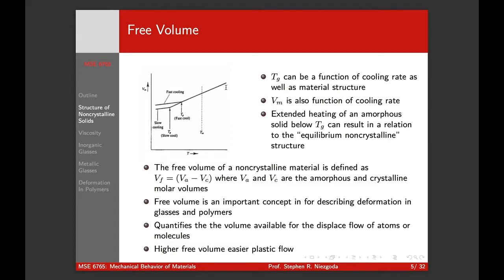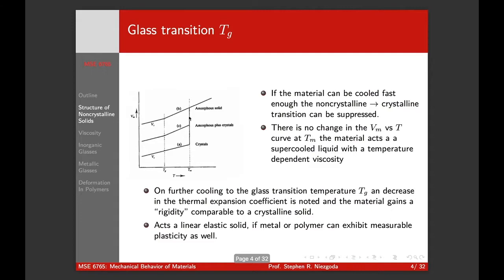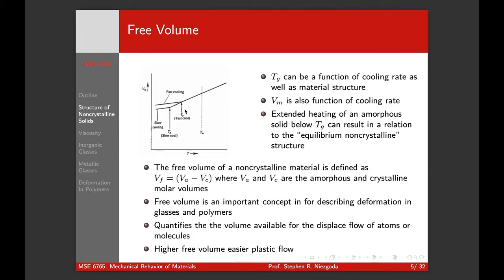Okay. So the glass transition temperature is not an intrinsic material property. It also depends on the processing. It depends on how fast you cool it.